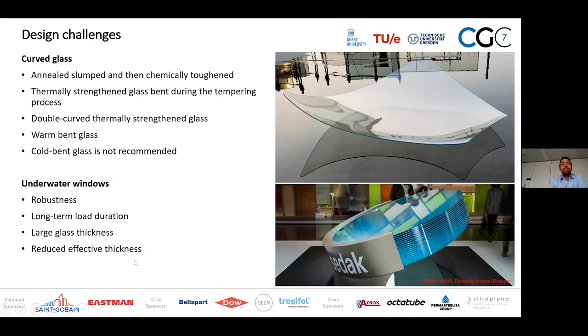And most of the authorities that check the design simply recommend to double the calculated glass thickness. Obviously, you end up with thicknesses like this on the right-hand side, where you have 18 plies, 8 millimeters thick, of fully toughened glass. Obviously, this is a quite stiff panel with reduced effective thickness.